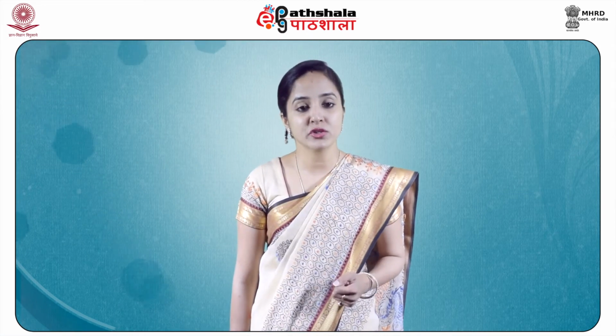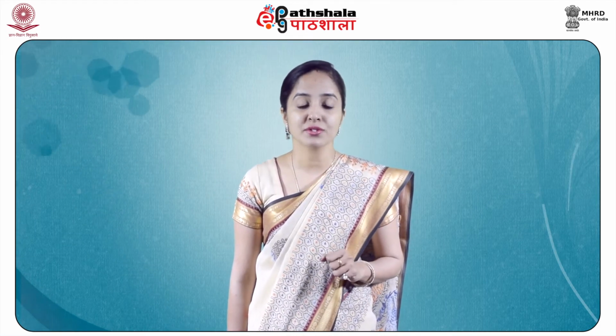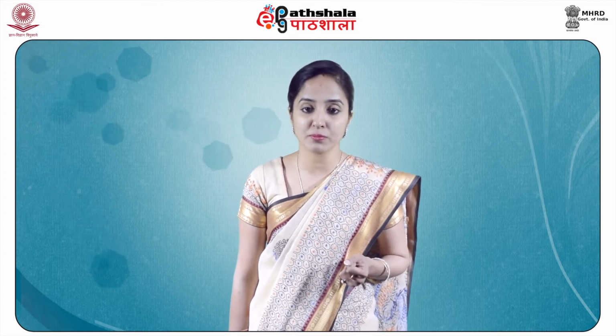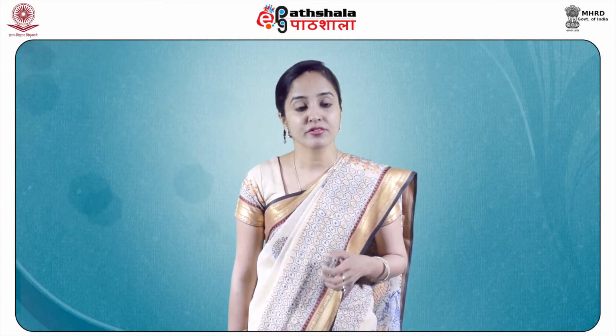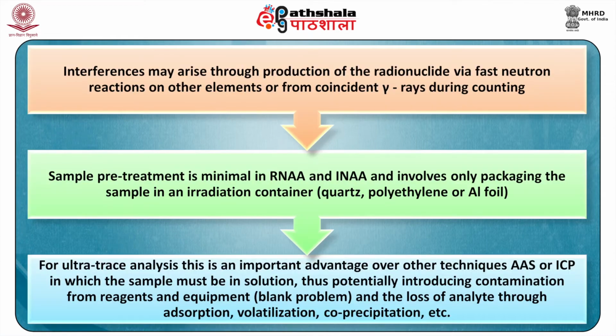The absence of matrix composition effects thus allows using standards that have different composition and even physical state from that of the sample. Interferences may arise through production of the radionuclide via fast neutron reactions on other elements or from coincident gamma rays during the counting process. Sample pre-treatment is minimal in RNAA and INAA and involves only packaging the sample in an irradiation container, that is quartz, polyethylene or aluminium foil.